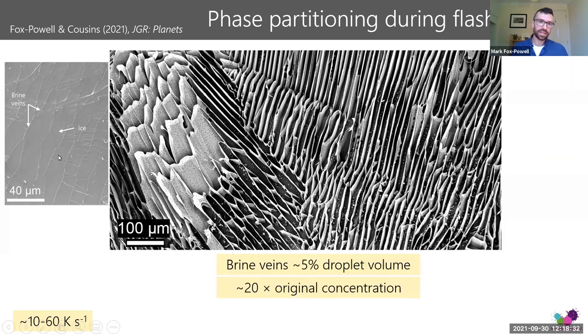By measuring the area and the volume of these brine veins, we were able to estimate that they occupy around 5% of the droplet volume, which means that the original solutes have been concentrated down into these brine veins around 20 times their original concentration, which exceeds the saturation points of many of the minerals predicted to form in this system.